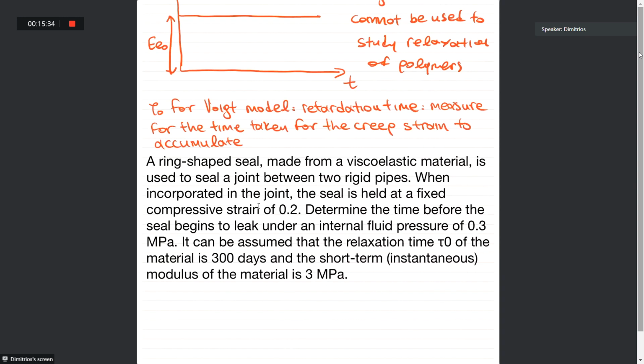Okay, so essentially we said that for the creep, we apply constant stress when we measure the strain, okay? So essentially it gives us how fast we will reach this maximum strain here, this creep strain. So the shorter the retardation time, that leads to a rapid creep strain.